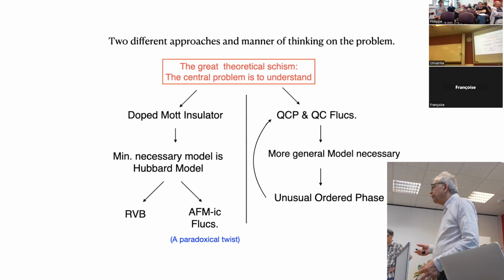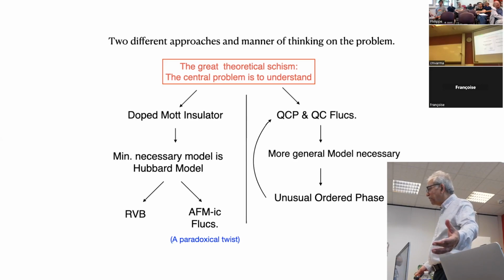For example, if you do experiments on cerium copper two silicon two, which you can dope to criticality by adding germanium, resistivity has been measured, specific heat has been measured, and you can make large enough crystals to do neutron scattering and measure chi double prime of Q and omega. You discover that the resistivity goes as T to the 1.6, and the typical Wilson-Fisher extension of classical critical phenomena works for cerium copper two silicon two, which is three-dimensional.